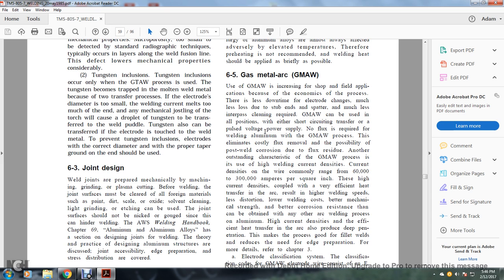No flux is required for welding aluminum with the gas metal arc welding process. This eliminates the costly flux removal and the possibility of post-weld corrosion from flux residue. Another outstanding characteristic of the process is the use of high welding current density in the wire, commonly in the range of 60,000 to 300,000 amperes per square inch. The high current density coupled with very efficient heat transfer in the arc results in higher welding speeds, low distortion, low welding costs, better mechanical strength, and better corrosion resistance than can be obtained with any other welding process.